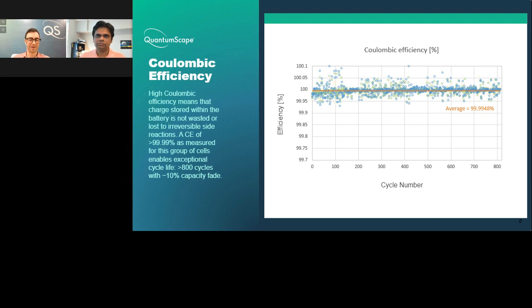But a further reason why you can have some noise here is we're actually down under the current resolution limits of these testers. So to get a much more precise measurement of coulombic efficiency, you would need a high precision Coulomb counter. And such devices are sold, but are not commonly used and were not used for this cycling test. So we're actually showing that the batteries are so efficient that they almost can't be measured by these standard measurement devices. Another way to make this roughly 99.995% efficiency more tangible is to think about 100,000 lithium atoms crossing the battery every charge and discharge, and 5 of them being lost somewhere. They wander off and react with some impurity in the battery or something like that. So that would roughly be 5 lithium atoms per 100,000 that get lost every cycle.